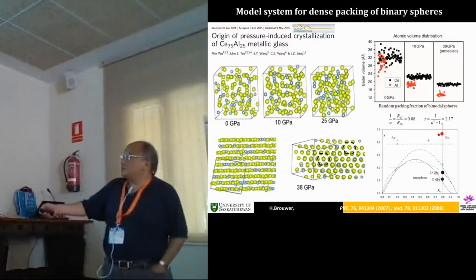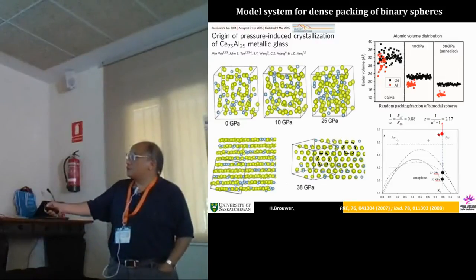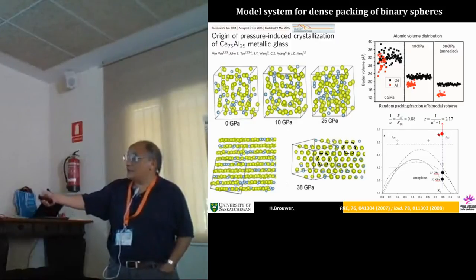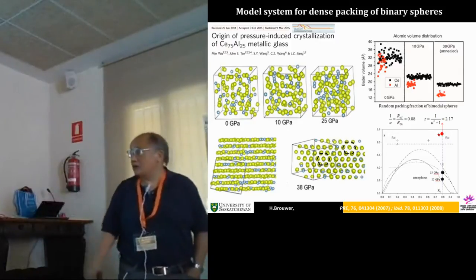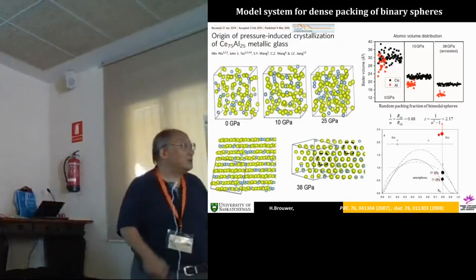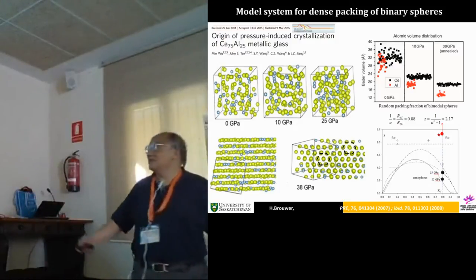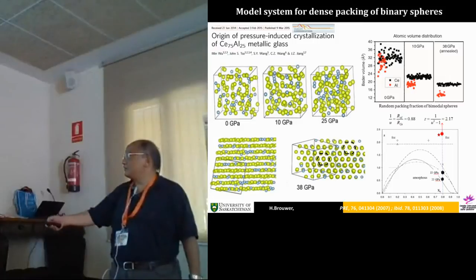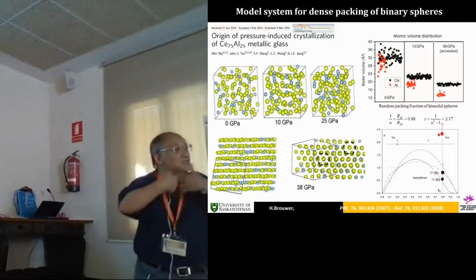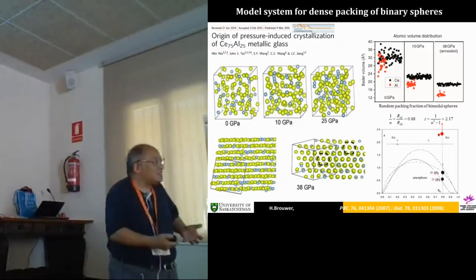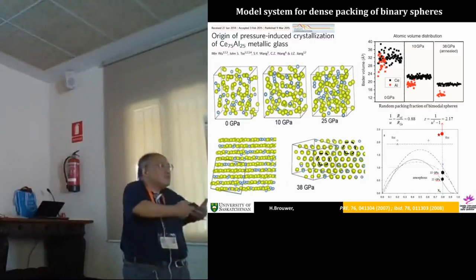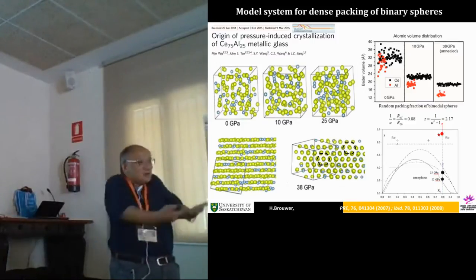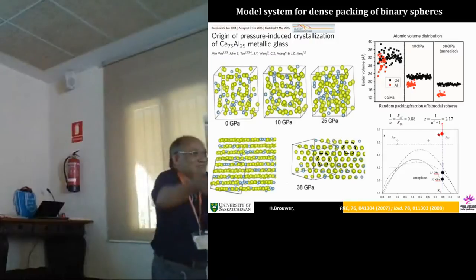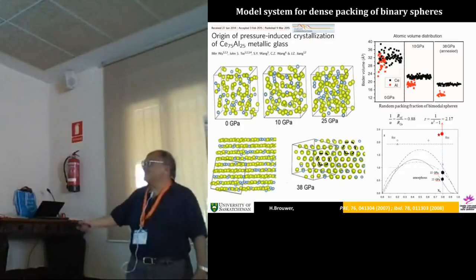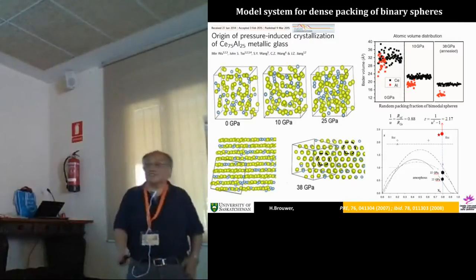So after they do that, normally if they have a three-dimensional solid, the density with the so-called first diffraction peak, strong diffraction peak of a glass should be three, because it's three-dimension. And they got around 2.5. So is the bonding in glass is not three-dimensional, but 2.5? Say two will be planar, right? One will be linear, they only interact linearly, right? So it's a lot of physics in there.